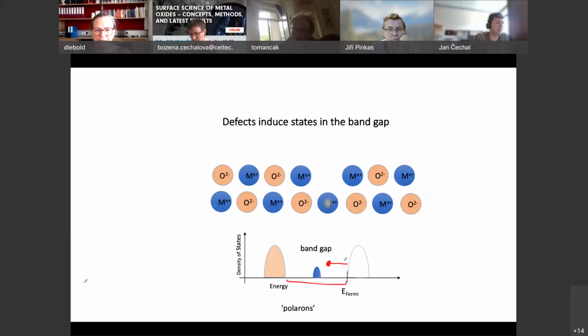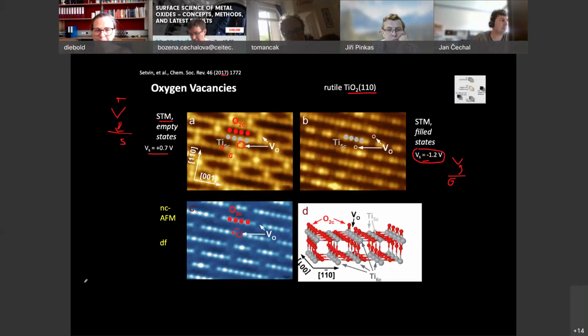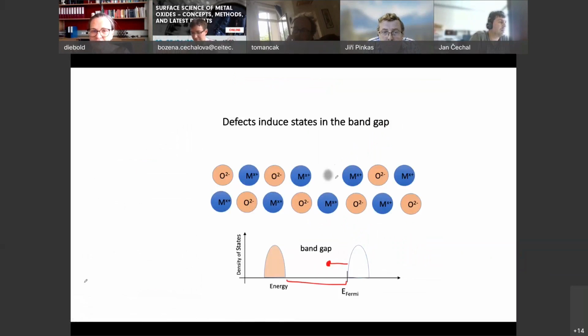So if you look, this is why this picture is so important, right? We know here, this is exactly the same area. We know here it's the oxygen vacancy. We can see the oxygen vacancy in the empty states very clearly as a bright feature, even though there's no atom. Now, in the filled states, you can see there's nothing. There's nothing here, there's nothing here, nothing here, nothing here. So the electron, that's what I try to show here. The oxygen goes away, it leaves the electron behind, but the electron doesn't stay in the vacancy. It moves to the next titanium atom and localizes there.